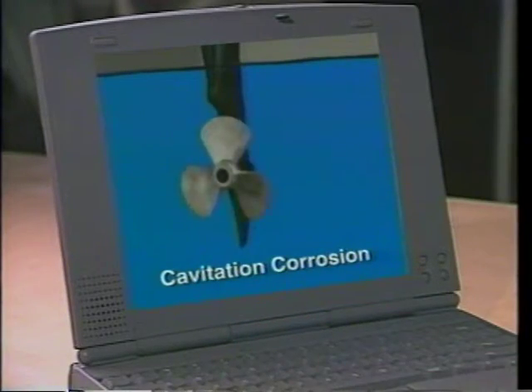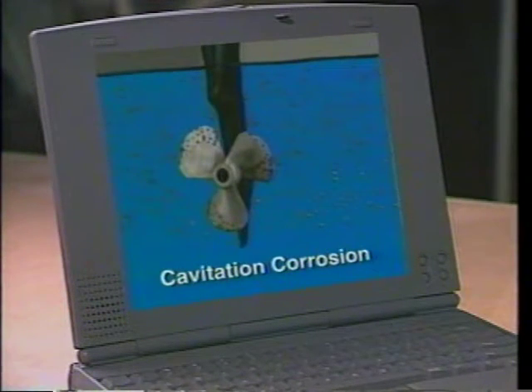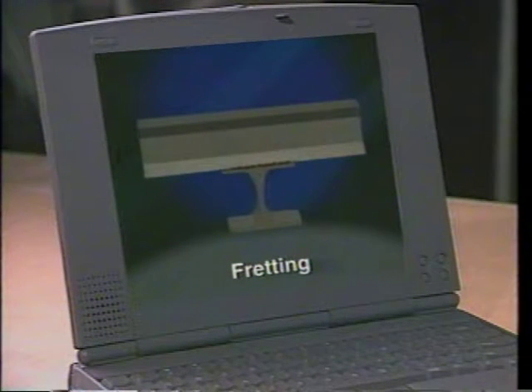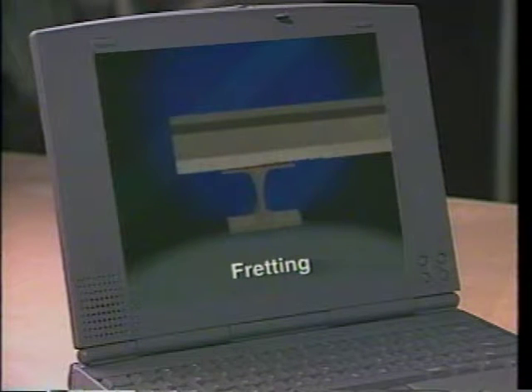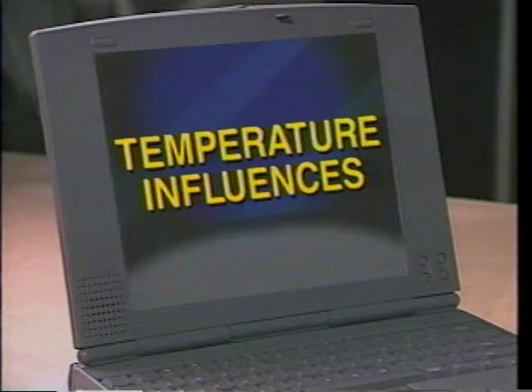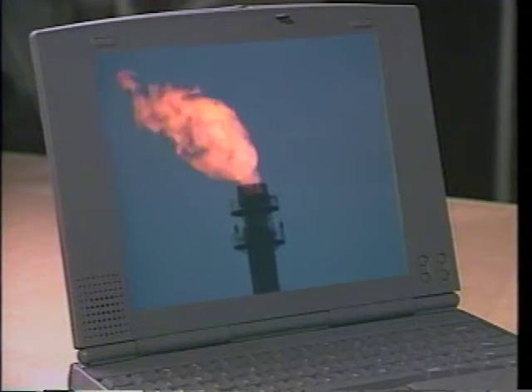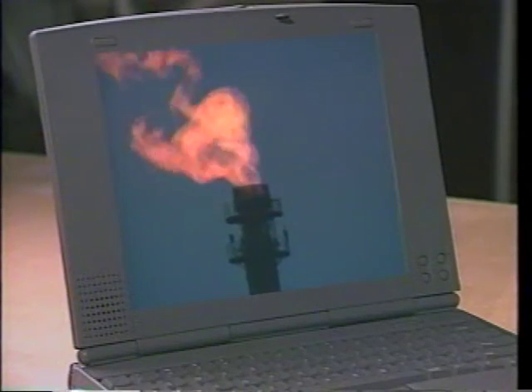Physical influences are the abrasive effects of any material, solid or liquid, whose constant movement across the surface of the metal hastens the damage caused by corrosion. There are many types of physical influences. Cavitation corrosion occurs when bubbles in a liquid constantly form and collapse, resulting in localized high pressure against a metal substrate. Fretting occurs when ongoing friction between two metal surfaces causes one or both to deteriorate. And finally, temperature influences can cause corrosion. When high temperature corrosion takes place, the electrolyte is a molten salt rather than being in an aqueous state.